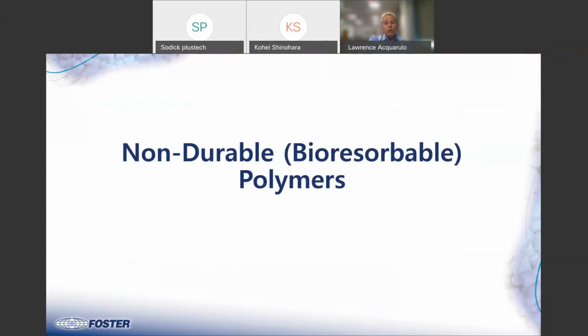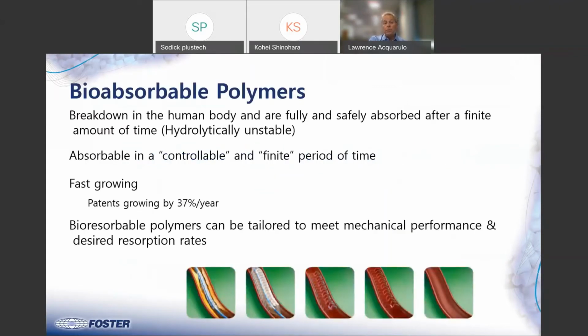So the non-durable or the bioresorbable, as I said, these materials break down in the body over time, and some of them do take a long time to fully and safely absorb. They are hydrolytically unstable, which is one of their outstanding properties, but it also makes them more difficult to manufacture, especially to process, because they degrade pretty readily, even during the melt processing stage or the storage stage. So very susceptible to moisture degradation and so forth. So there is a lot of special handling that you need.